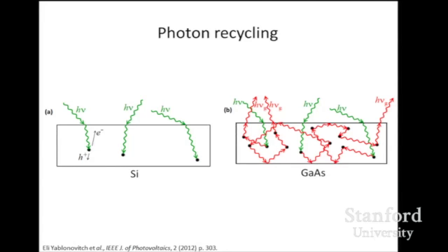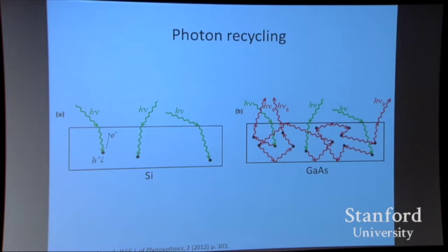One thing that's been really interesting to see in the last few years is that the approach also made the solar cells better. Not only were they cheaper, they actually work better than the solar cells where you leave the gallium arsenide on the substrate. And Eli Yablonovitch has shown us that that's due to photon recycling. In gallium arsenide, non-radiative recombination is so rare that almost all recombination results in a photon being emitted. And that photon can simply be reabsorbed, regenerating the carriers.